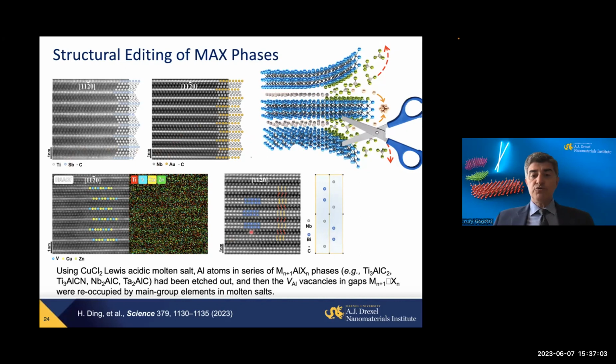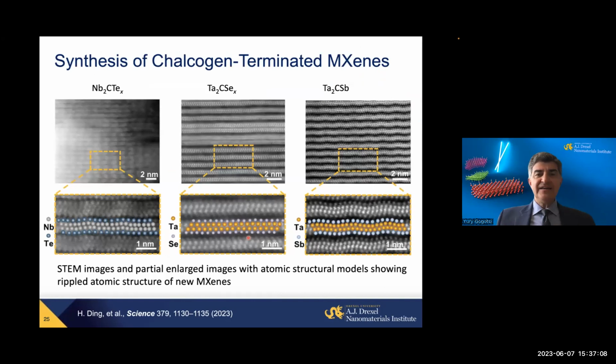It can be two atomic layers instead of one. And then we can etch away, again, a monatomic layer, imagine over 10, 30, 40 microns, we can etch a monatomic layer away. And then get the terminations we want. For example, here is niobium terminated with tellurium, tantalum carbide terminated with selenium, or for the first time, antimony termination shown on tantalum carbide. And of course, those are just a few examples of chemistries that we can achieve here.